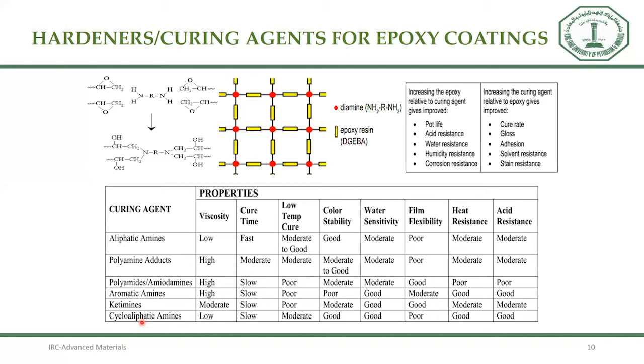For example, when you increase the epoxy relative to the curing agent, we can improve the pot life as well as the resistance toward acids, water, humidity, and corrosion. When you increase the curing agent relative to epoxy, we can increase the curing rate and glossy appearance, adhesion, and solvent resistance and stain resistance.